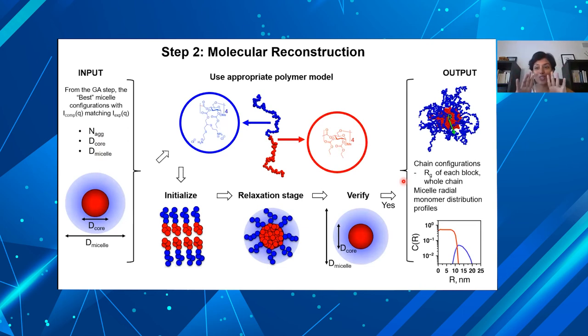And then you can get concentration profiles. How mixed or demixed are the two domains? Is the interface rough or smooth? You can see that in the concentration profile. It's a lot of information that you want to get for that structure beyond analytical models, even if you had a good analytical model. So these are the two main steps.